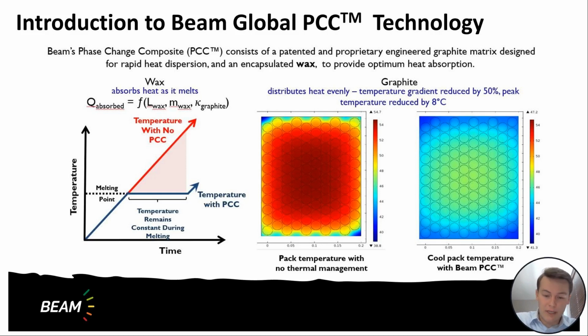And so distributing the heat, as well as managing maximum temperature, which we do through the heat absorption of the phase change. So as the battery pack temperature heats up, the wax goes from a solid to liquid transition, and that absorbs an enormous amount of heat compared to specific heat absorption products like metallic materials. And that allows us to cap battery pack temperature, and obviously simultaneously distributing the heat uniformly as well. So you have low pack temperatures, but also uniform pack temperatures.